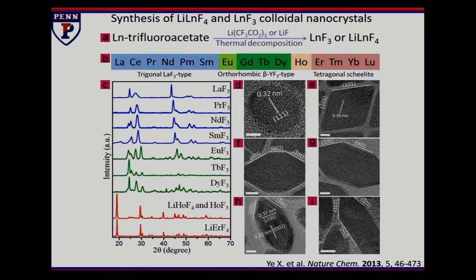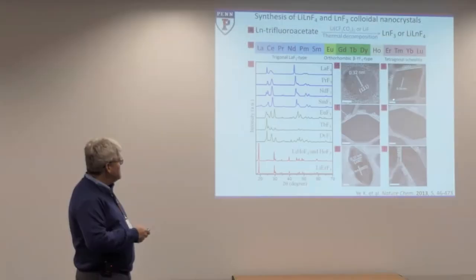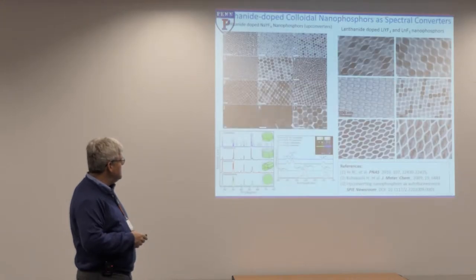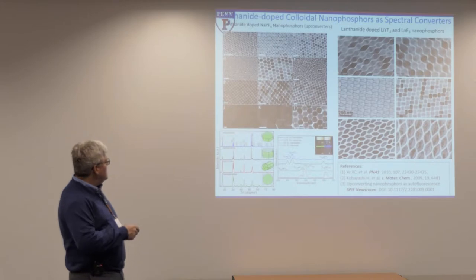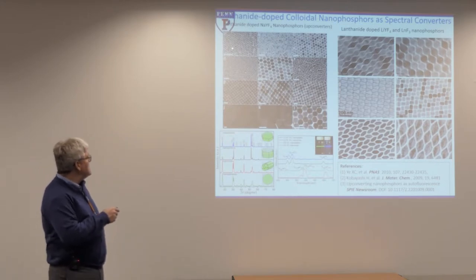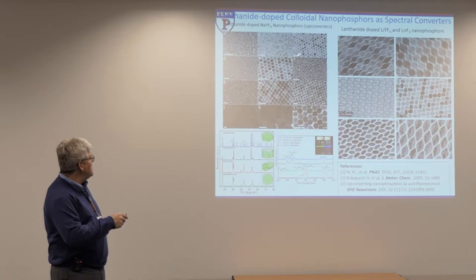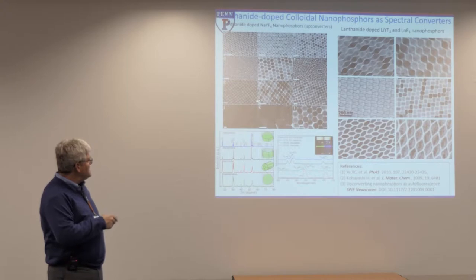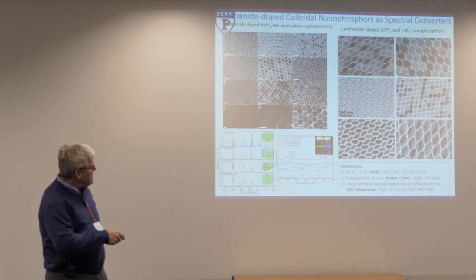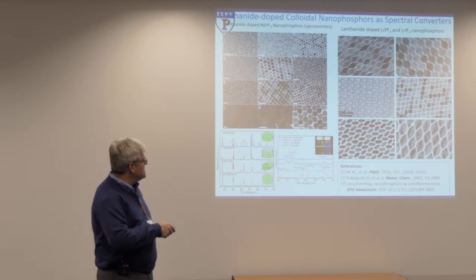So we began carrying out synthetic processes to see if we could do a little bit more in terms of engineering the geometries and structures. So let me just show a couple of images here. So these are families in which you adjust the shape of the particles or size of the particles, but these systems span from few nanometers up to hundreds of nanometers, but they do allow quite exquisite control of the size and faceting and ultimately even the surface termination of these systems.